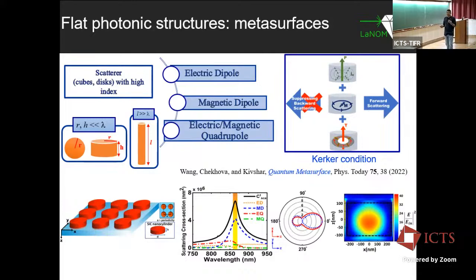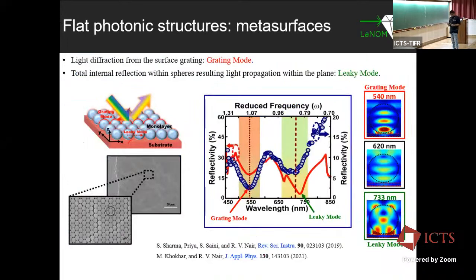And once the electric field is localized, your dipole moment dot electric field, you can enhance the local density of photon states. This is the whole idea of what people nowadays talk about as quantum metasurfaces. You have these systems where you create quantum emitters in individual scatterers, and you play with these multipolar contributions. So we thought, since we were able to make a multilayer structure, it would be easy to make a single layer structure. And it turns out it was even much more difficult to make these structures, these single layers of polystyrene spheres.